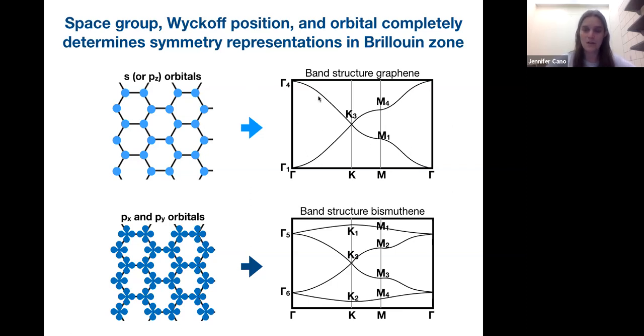The dispersion will depend on the hopping magnitudes between different sites, but you cannot avoid having this, what we know as the Dirac cone in graphene. You absolutely cannot avoid this because this is transforming in a special way under symmetry, and we can completely get the symmetry in momentum space from how these atoms transform into each other in real space. And similarly, if we were to look at px and py orbitals, which is a different orbital content, and plot a band structure, you will always get a band structure that looks like this. It has a Dirac point, but it also has two single bands. And now there's some freedom, which is that you don't know from symmetry the order of these bands at each k point, but you can know their symmetry labels. And so it highly constrains the sorts of band structures that you can get. And all the symmetry labels are completely determined by how the orbitals and atoms transform in real space.